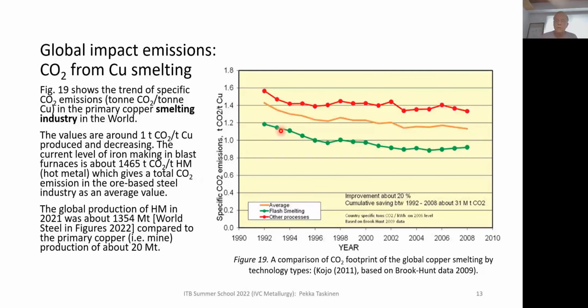But what is important in this figure is that we have flash smelting technologies which are and have been always emitting less CO2 than these other processes which are producing, how to say, probably 10% more than the average and 20% more than flash smelting technologies. And this is coming actually from the use of external energy in the smelting, which is low in the case of flash smelting.